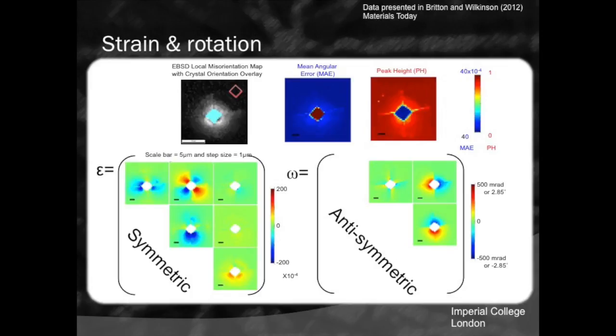If I push my finger into a piece of plasticine and release, the crystal pushes back against my finger — I get a compressive stress along the direction I'm measuring. And indeed, my silicon pushes back against the indenter. Looking at the next tensor component, the crystal is pushing back differently because the sample was very slightly misaligned during indentation, which is why the lobes are not quite symmetric — but it still looks pretty good.